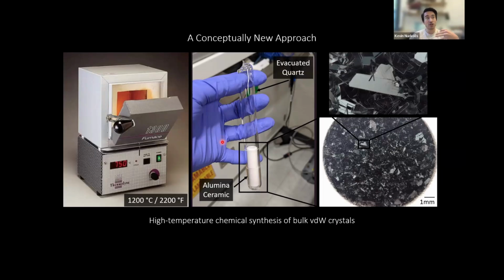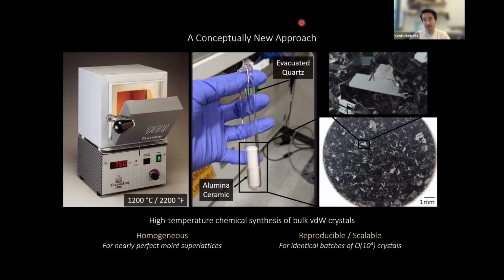So the idea is that we're actually going to try to grow with solid-state chemistry bulk crystals that have all of the salient features of Moiré materials and probe their physical properties. And the key advantages of this approach are the fact that because we're growing these Moiré materials in thermodynamic equilibrium, they'll be highly homogeneous. The Moiré superlattices in these compounds will be nearly perfect throughout the entire volume of these millimeter-sized crystals. And because we're growing these crystals using solid-state chemistry, the Moiré superlattices are highly reproducible and potentially scalable for next-generation electronics that leverage Moiré materials.